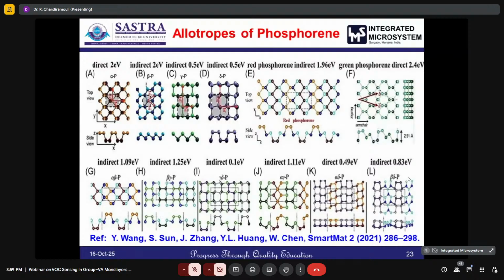So these are the various allotropes of phosphorene. Apart from the different thicknesses, we can also fine-tune the base material phosphorene by different allotropes. Here we can see a number of allotropes of phosphorene, starting from alpha, beta, gamma, delta. Alpha is a puckered structure, beta is a buckled structure, gamma is somewhat like a sawtooth structure, and delta is also somewhat related to the puckered structure. Alpha phosphorene possesses a direct energy band gap of 2 electron volt, and the beta also has the same band gap of around 2 electron volt, but it is indirect.